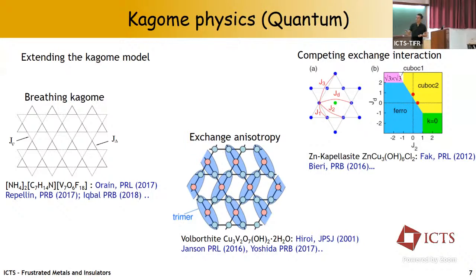Another way, which is a bit more drastic, is to imagine models with anisotropy of the exchange. I mean, nearest neighbor interactions, but which are different on the bonds, on the three bonds of one triangle. So now we don't have perfect triangles anymore, but triangles with maybe two different exchanges or maybe even three. Okay. So that was a model proposed at some point to explain, for instance, volborthite. So usually when you do that, you tend to go to long-range order quite easily. Now, the model, so volborthite, it's quite interesting.